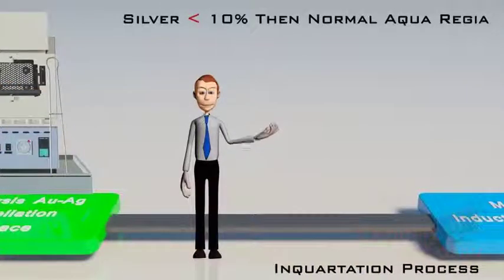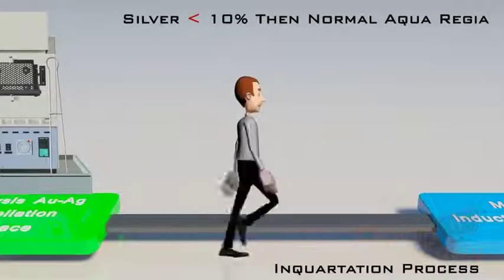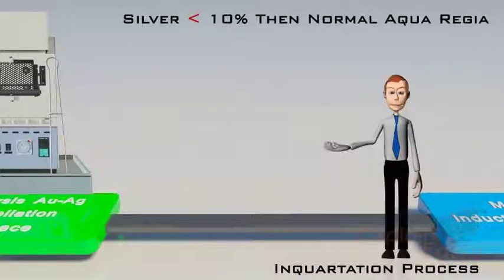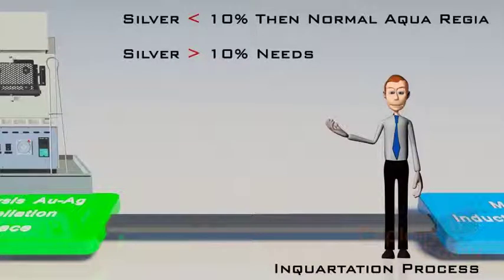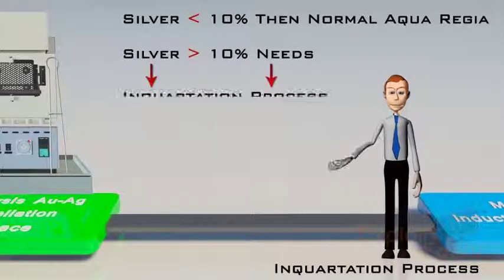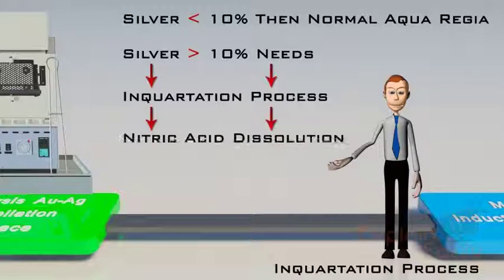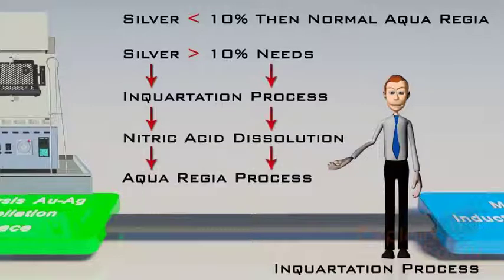refining. If silver is less than 10%, the normal aqua regia process is to be followed for refining gold, whereas more silver content needs certain steps to be followed, like inquartation process, nitric acid dissolution, and then aqua regia process. We have also developed a specific technology to process silver contents up to 18% directly by aqua regia process.